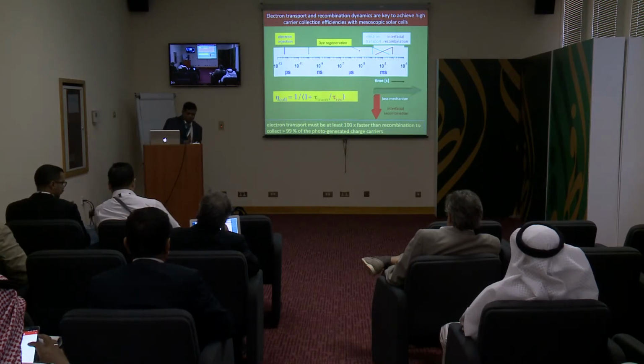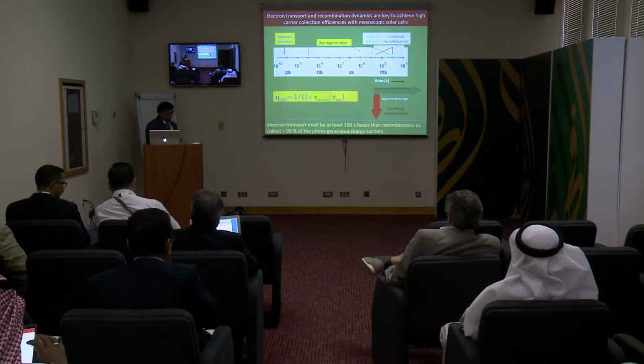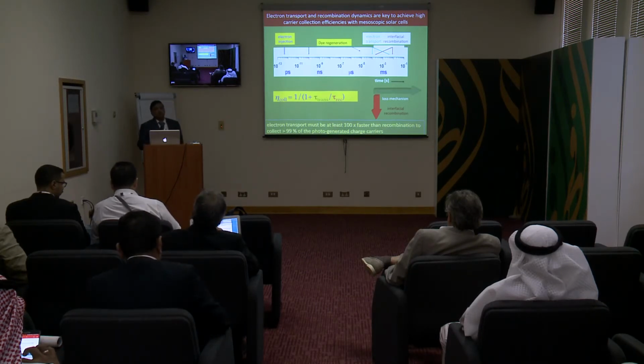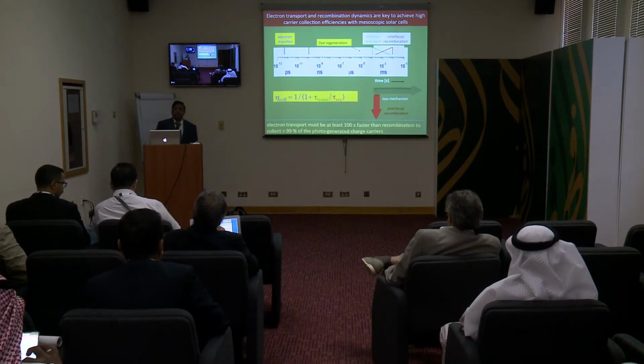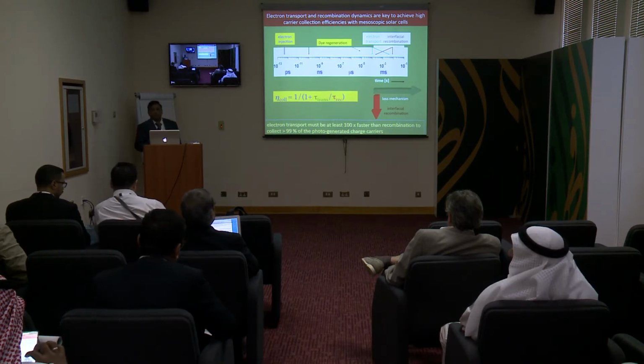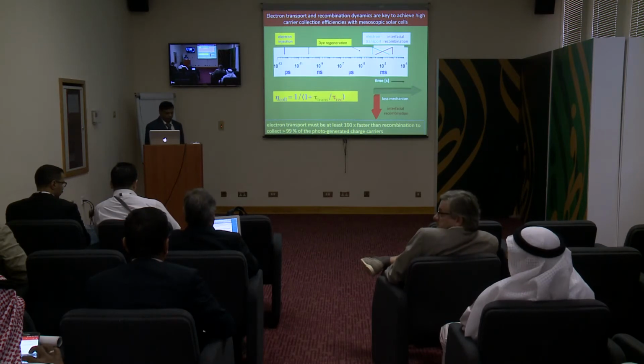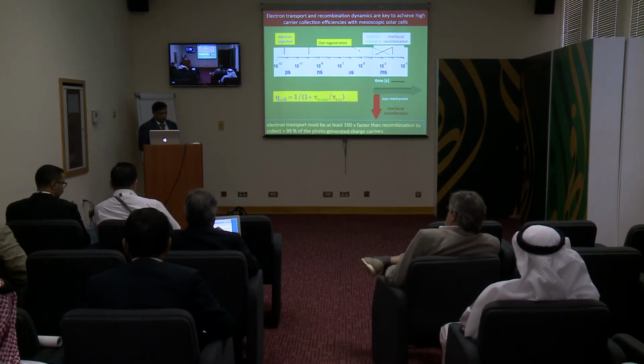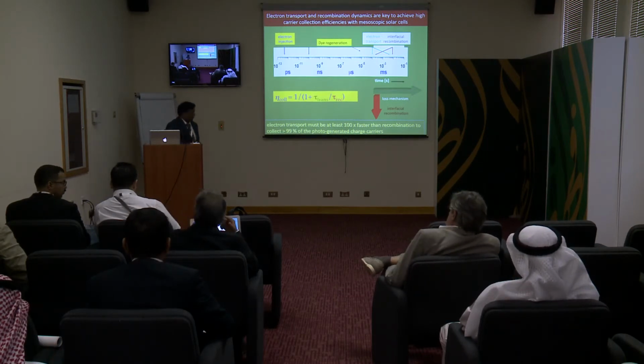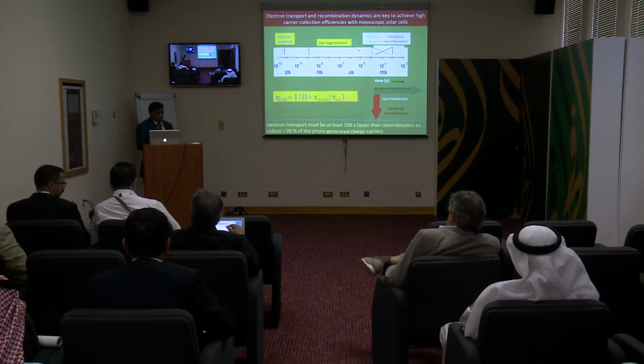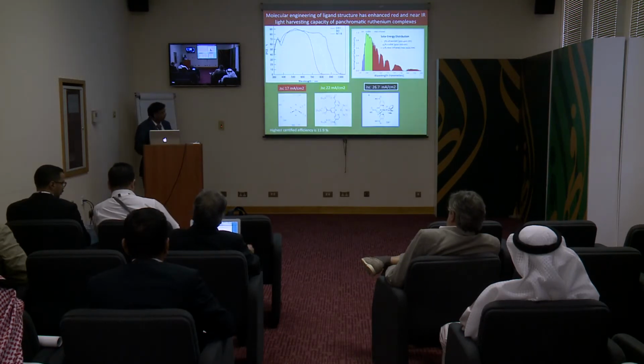So it shows that one can reduce the film thickness to come out of this bottleneck problem. But to do this, one needs high molar extinction coefficient dyes that give you thinner films with no effect on the photovoltaic performance. So that shows the importance of high molar extinction coefficient dyes.